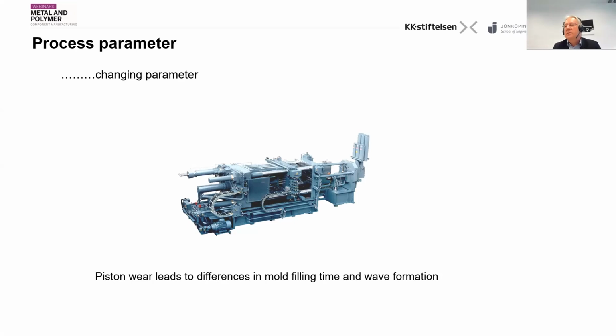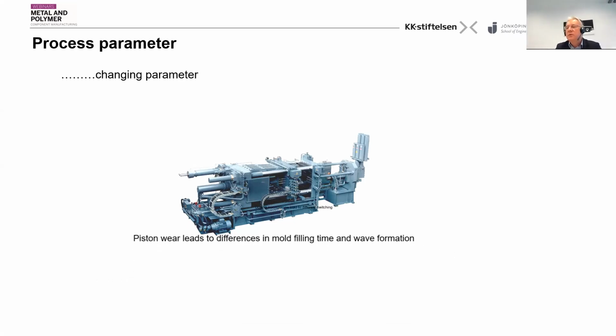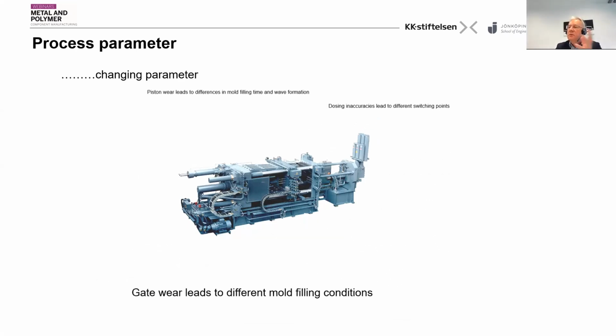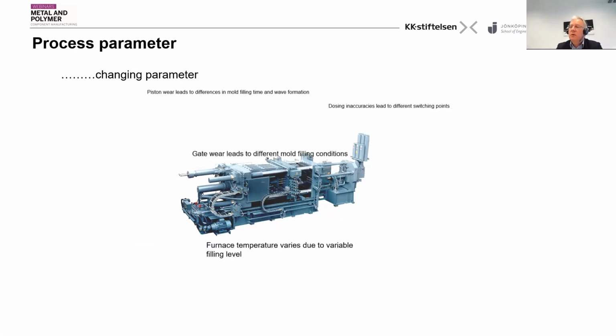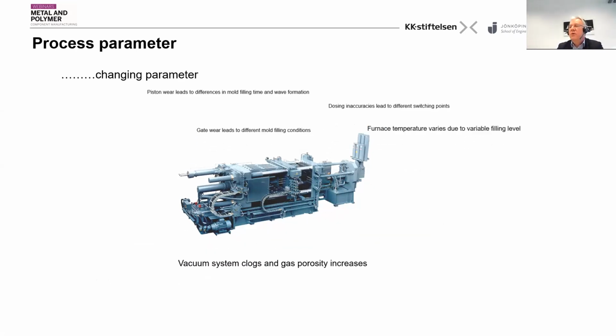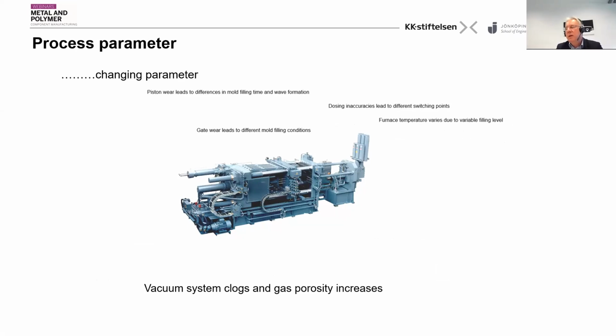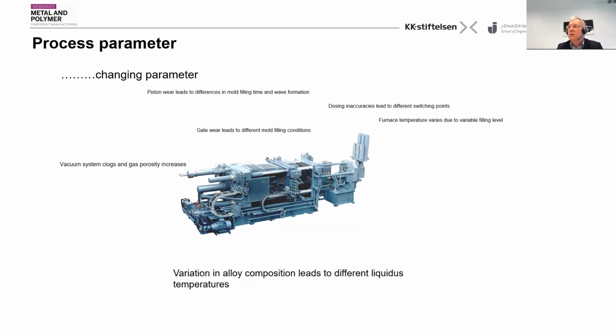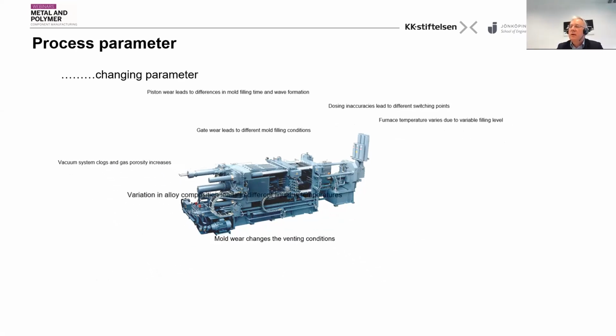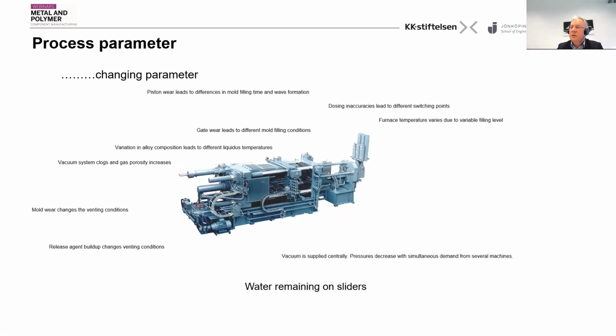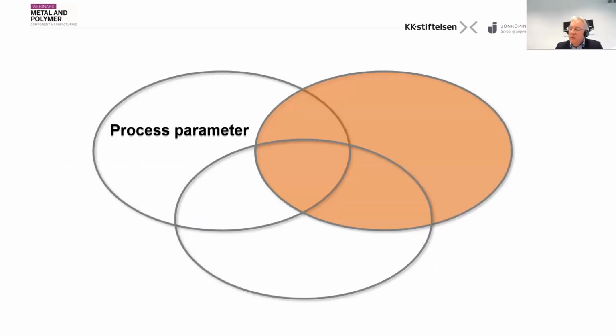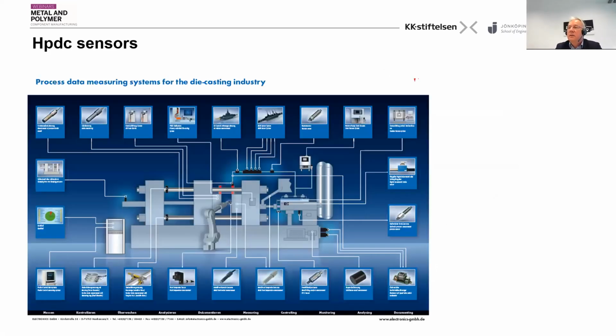But we also have parameters like these. They change during the process. Piston wear, or dosing changes, or gate wear, or furnace temperatures vary because people put fresh liquid metal in with another temperature, which changes the process as well. So we can talk about parameters again for at least half an hour, only about those which change. So the big thing is we have a lot of process parameters. Now we need sensors to control it, because later quality analysis and forecast is a goal.